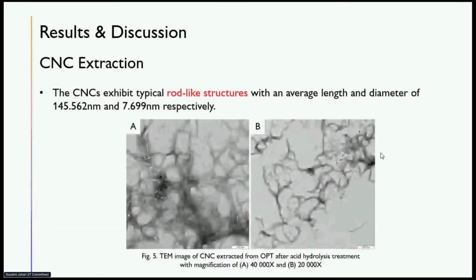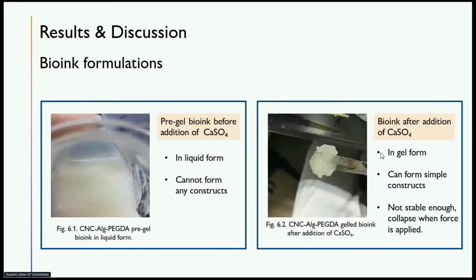This is the TEM image of the extracted CNCs. They exhibit typical rod-like structures, and the geometric distributions and the size of the CNCs differ based on the method of preparation as well as the source of the fiber. Here, the extracted CNCs have an average length and diameter of 145 nanometer and 7.7 nanometer respectively. Next slide. Now we go to the bioink formulations.